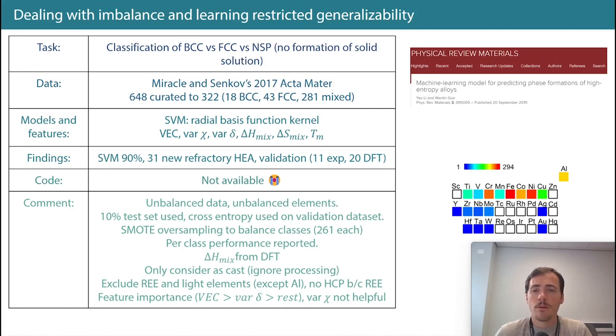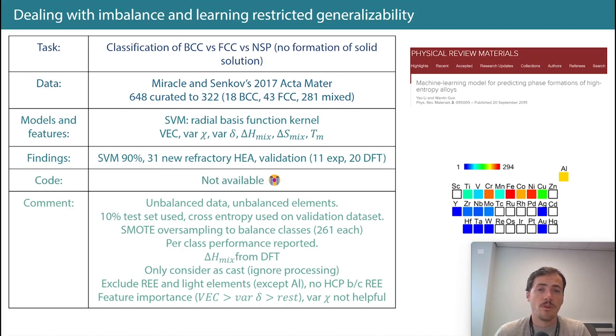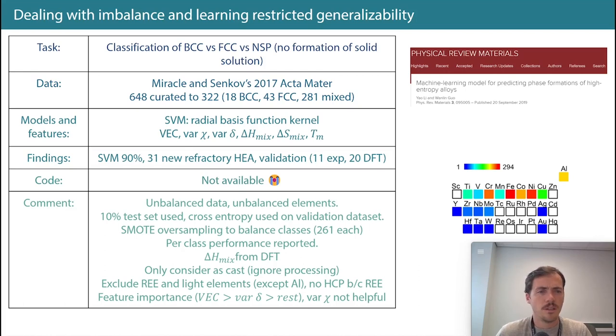How did they do? They report 90% performance. They then go on to predict 31 new refractory HEAs, actually test 11 of them experimentally and 20 via DFT to validate how well their model did. So some experimental and simulation validation went along with this. They did not provide their code or data.